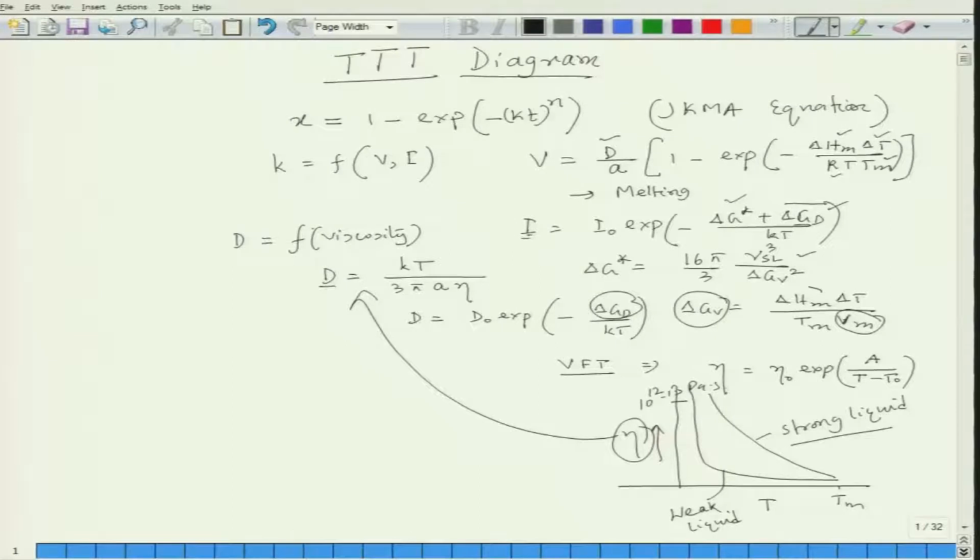We can also find out del Hm from DSC, which is differential scanning calorimetry, and del T, the temperature where we would like to take the liquid metal for solidification. And if I come to this part, which is gamma SL, it is a little tricky to find out, but experimentally this also can be found out by doing a controlled undercooling experiment.